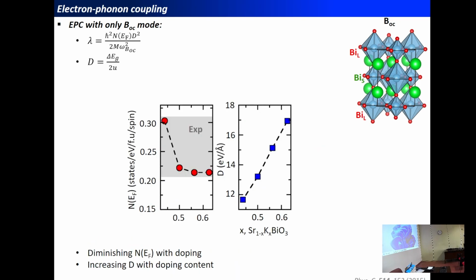So the next quantity, the reduced electron-phonon coupling matrix element, we can track it upon the doping content. And so we start with a value around 12. And then if you put more and more holes in the system, you see that this reduced electron-phonon coupling matrix element is constantly increasing. And therefore, you cannot just compute this term at a given value expecting it to be the same for the other doping contents. You have to precisely compute it at each doping content in this system.